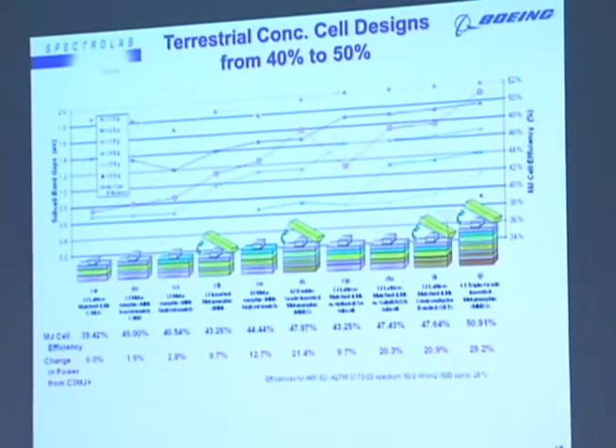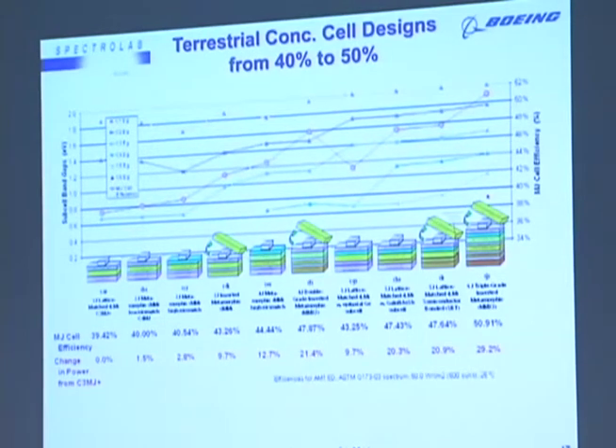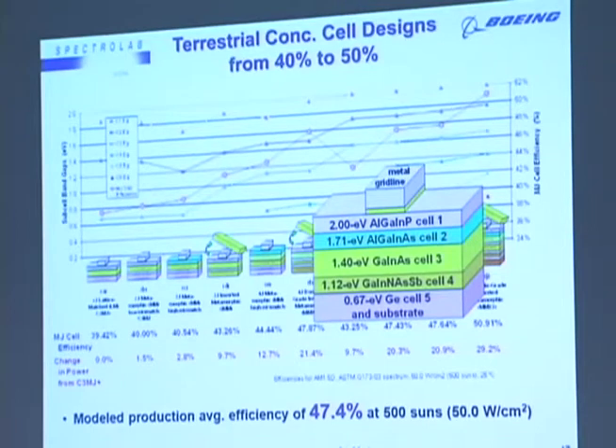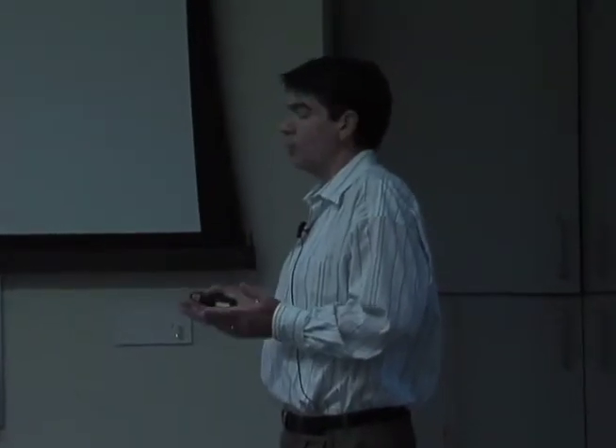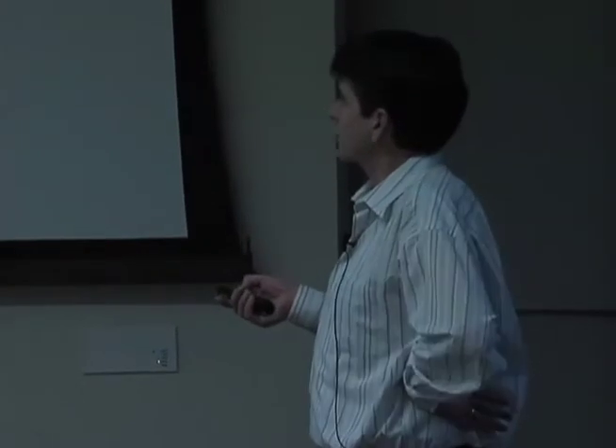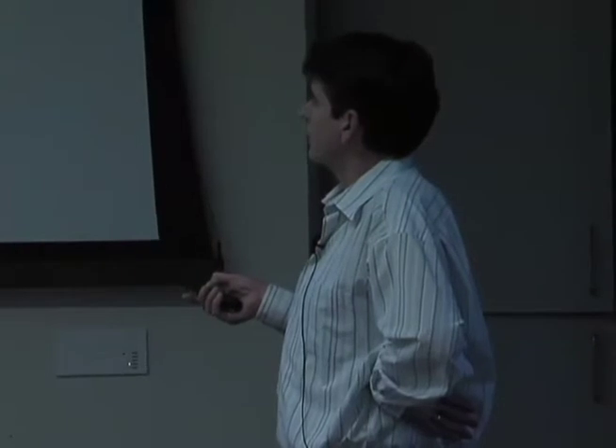So gallium indium nitride arsenide is a very interesting material, as I mentioned briefly earlier. One of the main advantages of that is that gallium indium nitride arsenide has an unusual and also very useful property that when you add this smaller atom of nitrogen, instead of making the band gap go up as it does with a small atom like phosphorus, the addition of nitrogen makes the band gap go down. So adding nitrogen to a gallium arsenide base composition can allow us to achieve band gaps in the 1 eV range, even at the gallium arsenide lattice constant. So we compensate the smaller atom of nitrogen with the larger atom of indium.